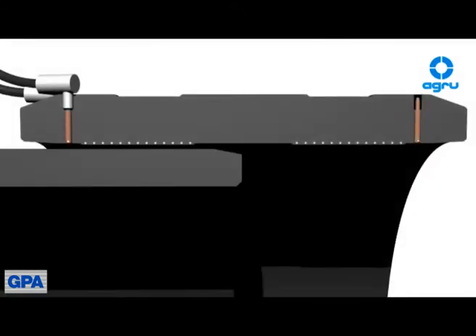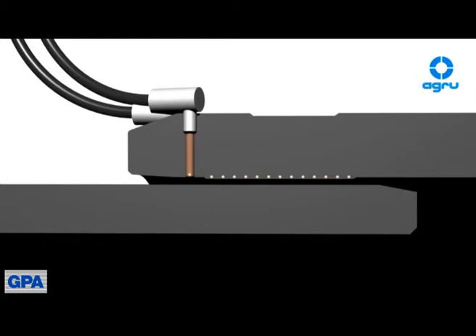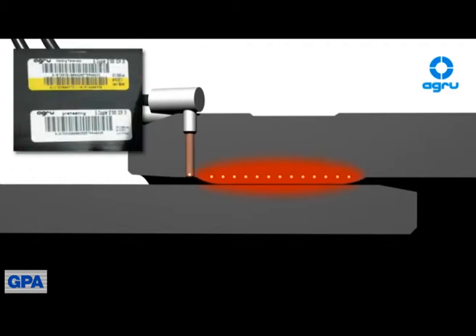For E-couplers from dimension 800 mm up to dimension 1400 mm, each side has its own electric circuit, also called bifilar system. Prior to welding each side of the coupler, the annular gap between the coupler and the pipe needs to be reduced with a preheating function. The programming of the preheating parameters is done by reading the white preheating barcode with a barcode pen or scanner. After the pre-cooling time is over, the gap has to be smaller than 2 mm, which can be checked with a feeler gauge. If the gap is okay, start the welding with a standard component barcode. If the gap is too big, repeat the preheating.